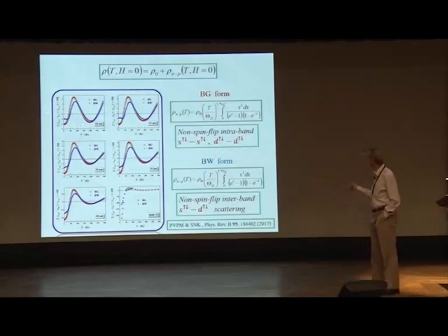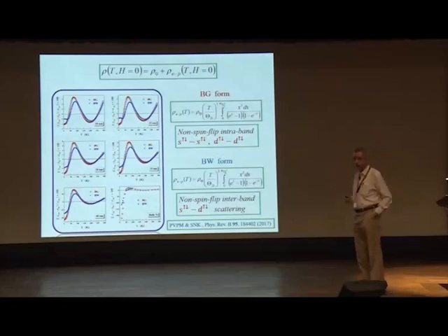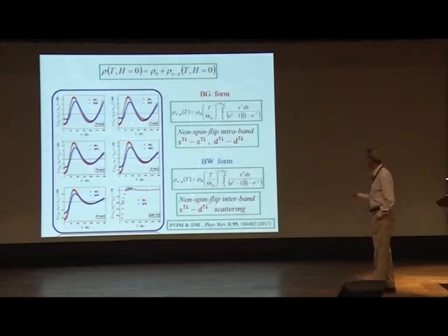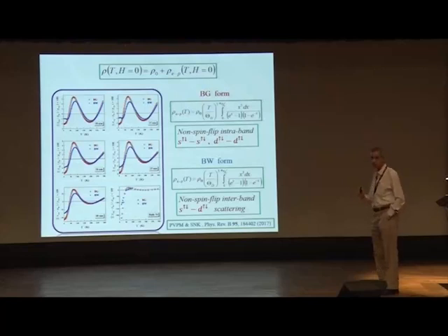That means this functional form, either this or this, does not really describe the observed temperature dependence. This we are doing from 1.8 Kelvin to 300 Kelvin. Between the two, the Bloch-Wilson form fits the data marginally better, but still with systematic deviations, telling us that is not really the form.